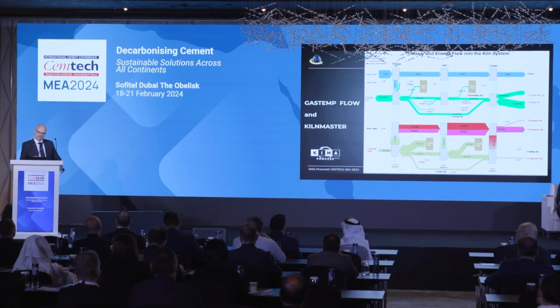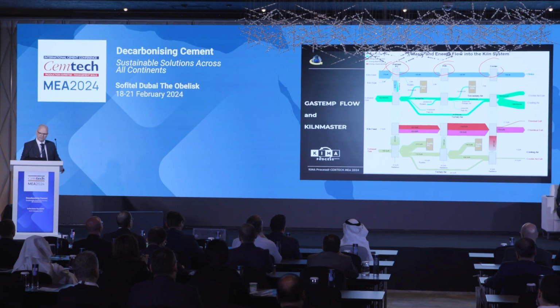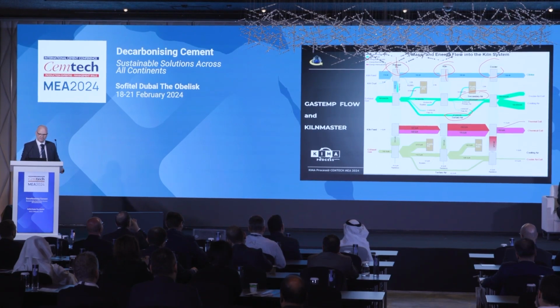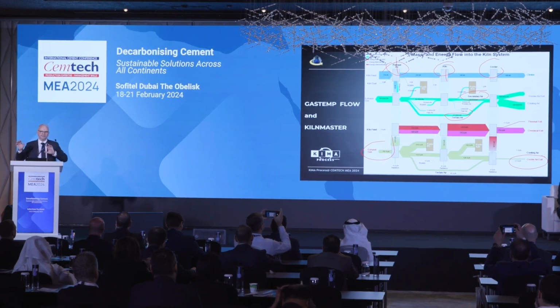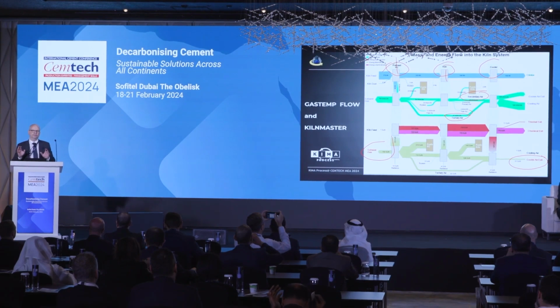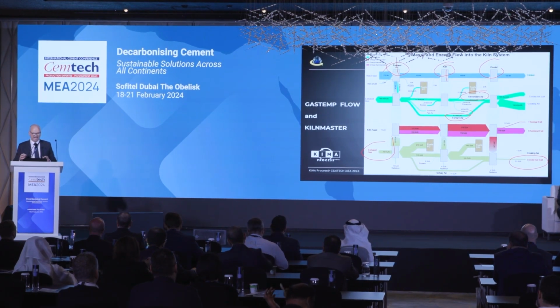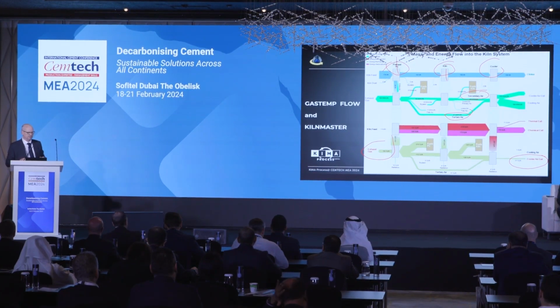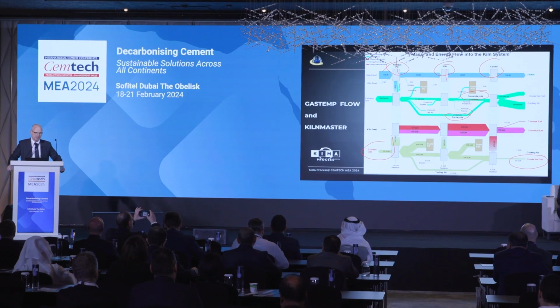Now, here we can see we have the preheater, we have the kiln, and we have the cooler. So all these three modules are in one big controller. And now we measure the gases. We measure tertiary air, we measure secondary air, we measure the downcomer, which is here, the exhaust gas, and we also measure the cooler exit. Now you can imagine that this is a very precise analysis of enthalpy flow, energy flow. This is new. And with the precision of these sensors, these instruments, it gives you opportunities to increase kiln production by between 5 and 10%.